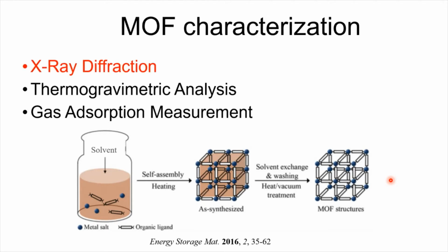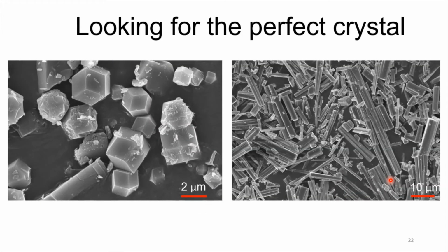But I do want to highlight how important X-ray diffraction is for us. Since we were working with new structures, single crystal X-ray diffraction is crucial. And if people have done some crystal growth for proteins or for other molecules, they know this is challenging. But if you haven't, let me just show you a couple of examples where you look at these crystals and they look really nice. But take, for example, the one on the left. They look really nice. You can see all the facets in the crystals, but once you see the size of those crystals, they are not suitable enough for single crystal X-ray diffraction. So you need to go back and change your synthesis conditions until you grow bigger, good quality crystals.